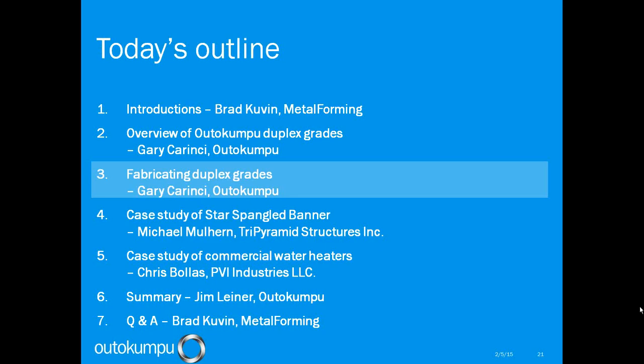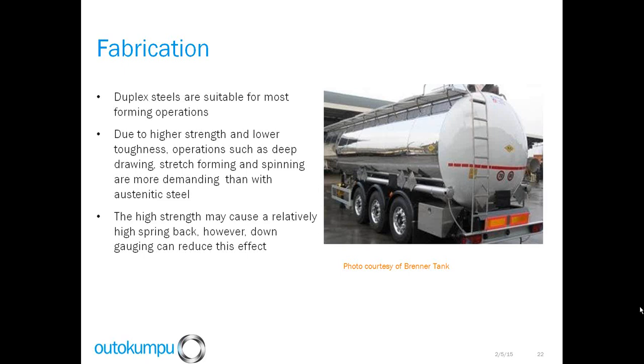Next, going to move into a brief discussion of fabricating with the duplex stainless steel grades. If we look overall at fabrication, duplex stainless steels can be used for many forming applications. They can be used for stretch forming, drawing, spinning applications, but the one thing you do find when you work with these materials is the high strength can cause a relatively high spring back effect, and down gauging in these applications, where you're using less force, can reduce this effect.